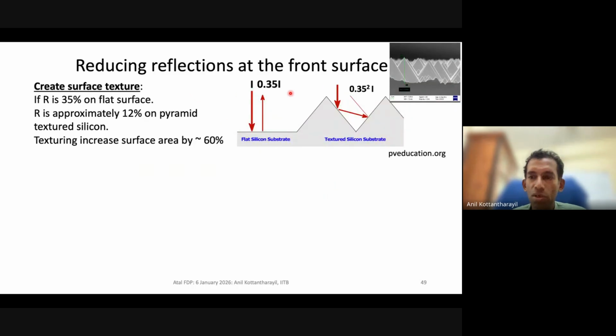So you can reduce the reflections by introducing this kind of structure. So the pyramids. I have shown that on previous slides on the front side of the solar cell. So it works like this. About 35% of the light gets reflected from a flat surface. Now, if you have a pyramid, the light is incident on the facet of this pyramid, and then 35% gets reflected. But this reflected light actually falls on the next pyramid. Okay, it does not go back to air, right? It just falls on the next pyramid, and then only 35% of that actually gets reflected. So the effective reflection is 0.35 squared. So that is about 12%. So from 35%, we reduce the reflections by creating this kind of pyramids to about 12%.